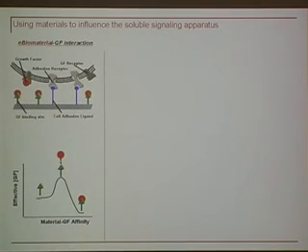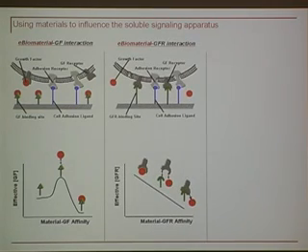So it's possible to engineer a biomaterial that can interact specifically with a particular growth factor, a soluble growth factor. Here the soluble growth factor is shown in red, the immobilized ligand shown in green, and then a cell adhesion ligand shown in blue. So in a system like this, a cell can attach to the surface, and that surface also regulates the availability of a soluble growth factor. And one can envision that as you change the material growth factor affinity, if the material is interacting with the growth factor active site, then there are possibilities of up or down regulating growth factor activity by tailoring the material properties. So we're doing this with a series of growth factors.